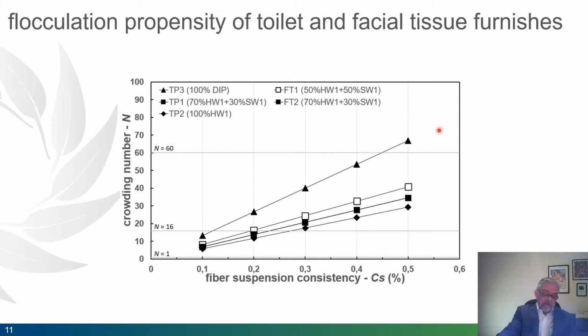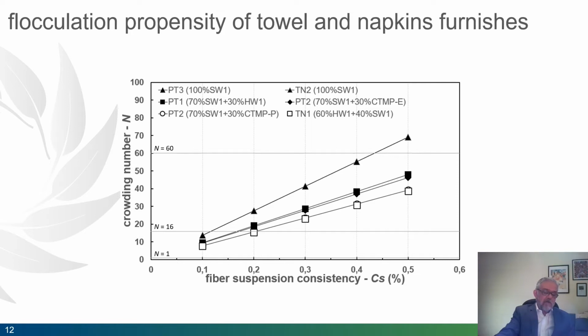A quite high flocculation propensity was found for the furnish based on 100% of DIP (deinked pulp). The selected deinked pulp contains very long fibers compared to other pulps in the same figure. If we look at the results for paper towel and napkins, we'll see similar results, but now I can emphasize the effect of pulps based 100% on long fibers, that is, on softwood. The higher flocculation potential belongs, as expected, to the towel and napkins furnishes made of 100% softwood, and both have similar behavior of the deinked pulp.